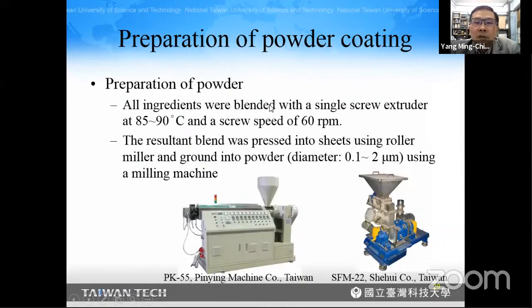All ingredients were blended using a single screw extruder at 85 to 90 degrees C, and the screw speed was 60 RPM. The resultant extrudate was pressed into sheet using a roller and ground into powder to a diameter of 0.1 to 2 micrometers. And this is a milling machine.